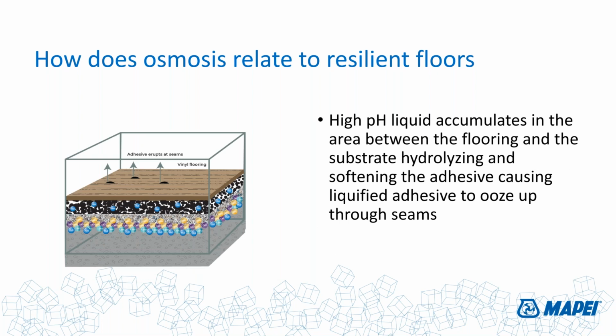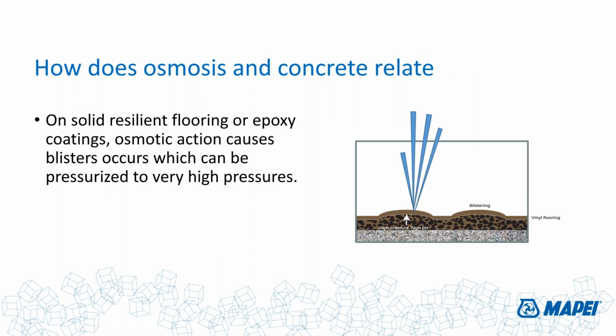This can even create enough pressure under epoxy membranes that you get this classic picture you've seen, where a guy's poking a knife in a sheet vinyl floor and you get water spraying out. Well, that's not water. It's a solution of chemicals, and you certainly wouldn't want it to get on you. You need to make sure you avoid doing that. But it's a chemical solution that builds up enough pressure to blister epoxy coatings and resilient floor covering installed with epoxy adhesives, or even PSAs or hard set acrylics. It can do all sorts of really bad things to you.